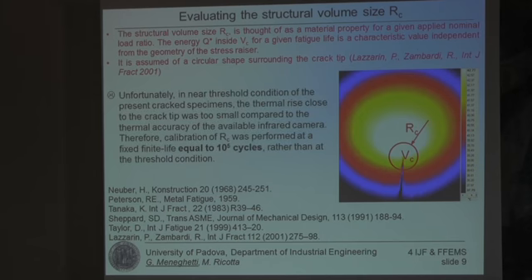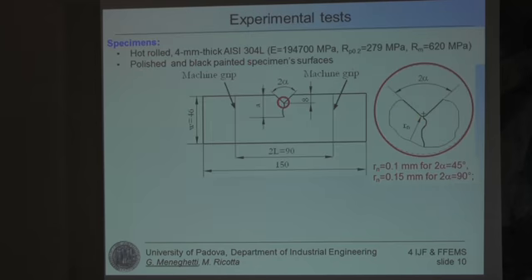Other choices might be possible. Now, in our case, unfortunately, in the near threshold condition of the crack, the thermal rise close to the crack tip was very small as compared to the thermal accuracy of the available infrared camera, so we could not calibrate the size of the structural volume at the threshold conditions. Therefore, we calibrated the size of the structural volume at a lower fatigue life, precisely equal to 10 to the 5 cycles, and not at the threshold. So, to determine the size of the structural volume, I have to present now our experiments, and then I will go back to the formula to evaluate RC.